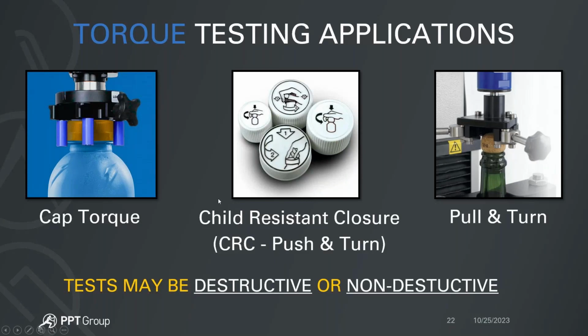Right. And then there is an extra dimension to this, which is the push and turn or the pull and turn cap torque testing, which is for child resistant closure or the CRC. Now, this is usually to activate a mechanism that allows you to uncap for safety reasons, right? And you'll find this in chemicals like bleach and so on. And you'll find this in prescription medication, again, to prevent people that that particular product is not intended for from getting into it, especially children and minors. And again, usually this involves applying a known axial force. What we usually do is apply a certified weight to simulate that push on force before you run that torque application to uncap, and then we measure both values.